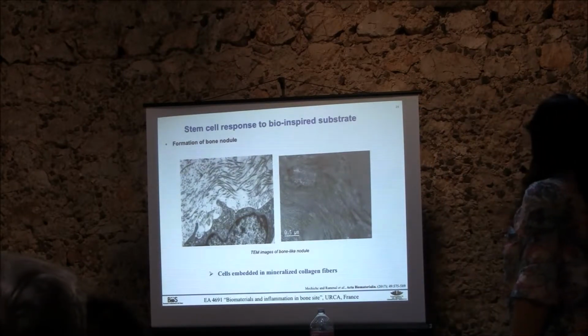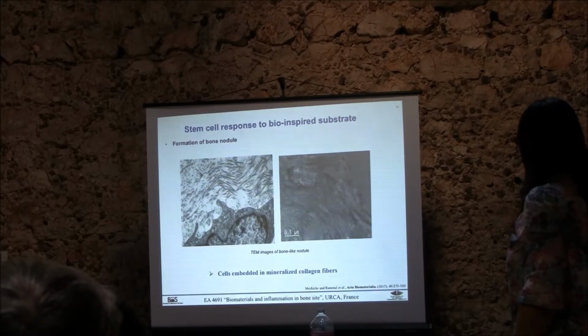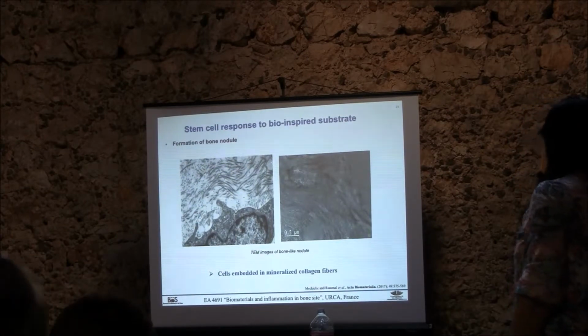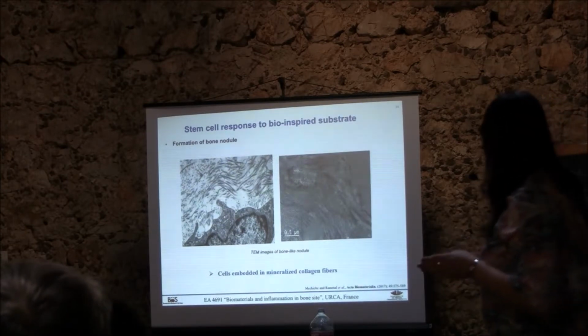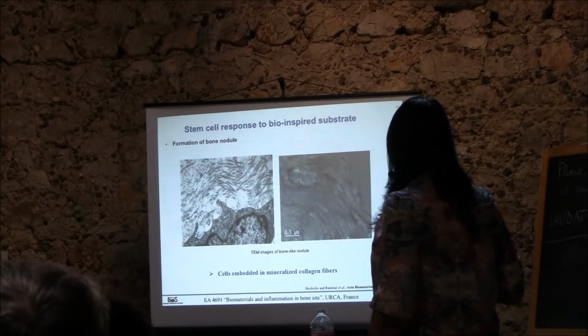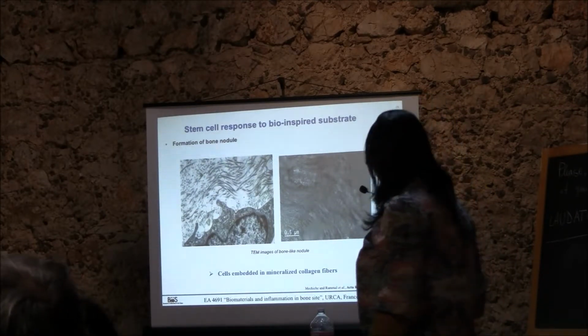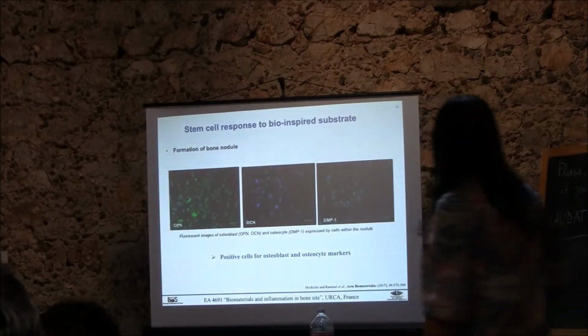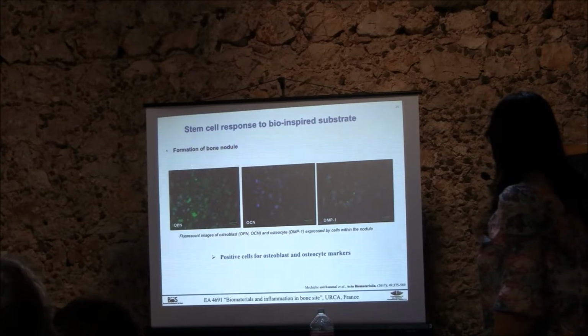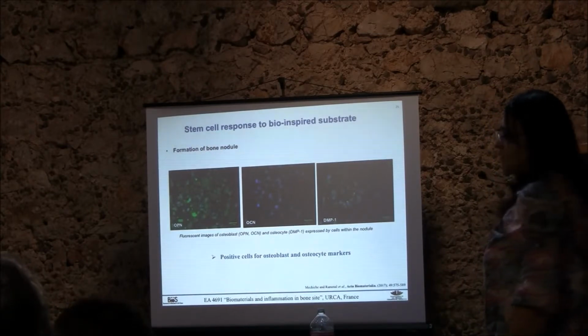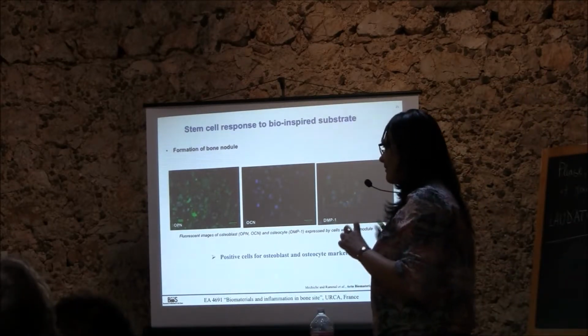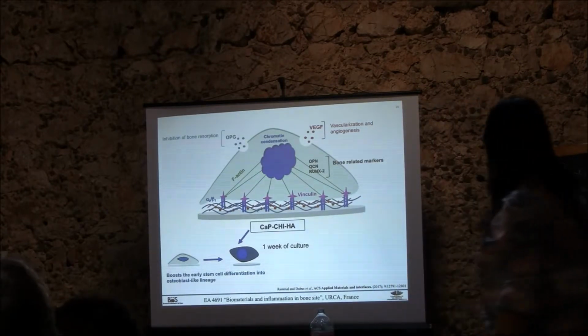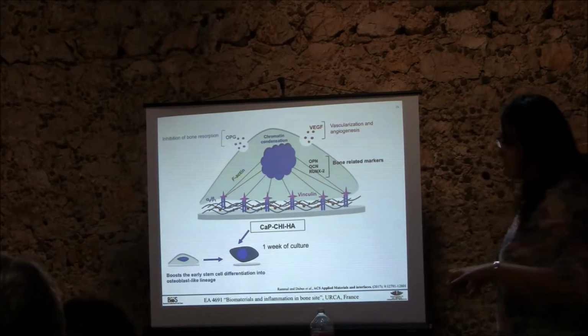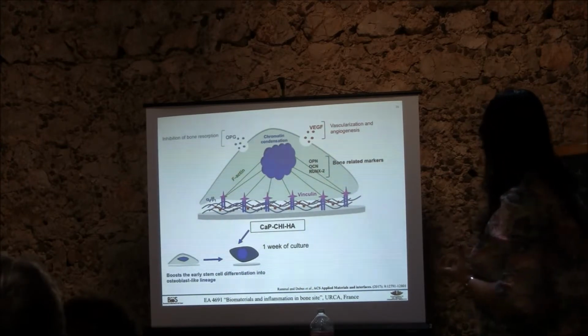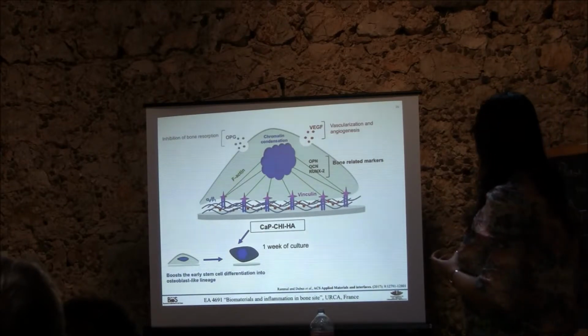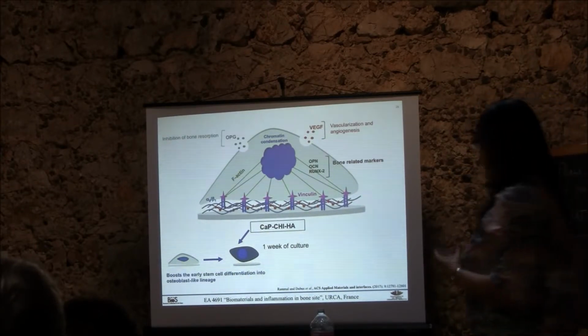And using transmission electron microscopy, we observed collagen fibrils with striation corresponding to collagen type 1, and we observed mineralization of collagen. Immunohistochemistry showed the presence of osteoblasts and also osteocytes in the bone-like nodule. So on our surface, we observed that cells are able to attach, to adopt a morphology in order to express bone markers and to release factors regulating bone regeneration.